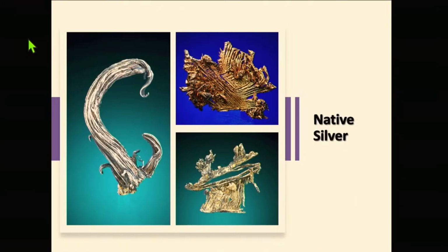and then these spectacular wires. That's a wire from Freiberg. Freiberg has been a special interest for me for many reasons, but that Freiberg wire stands about 6.5 inches tall. And if I take just that silver and I convert it to the acanthite that it must grow to, I get a block of acanthite that's about 1 foot by 1 foot by 1 foot. So what you're looking at is a large-scale decomposition of another mineral to be able to make that. So keep those kind of in the background.